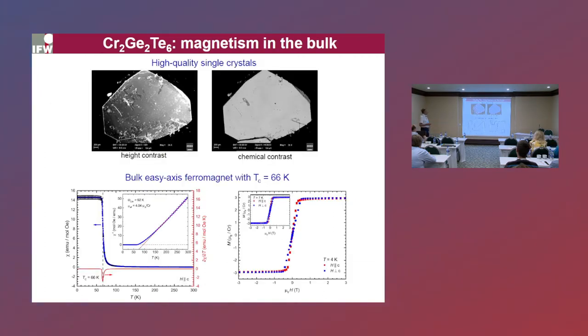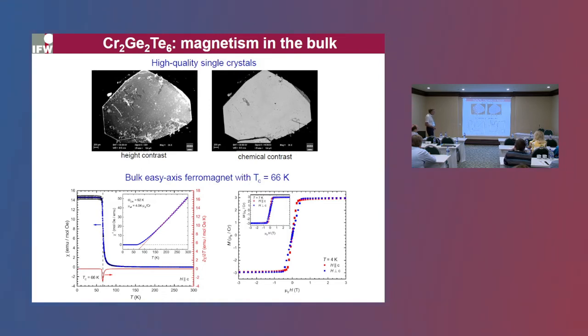Insights on magnetic anisotropy were required, and we attempted to obtain them in our measurements. We grew high-quality single crystals of this material — very flat and chemically homogeneous. We confirmed that in magnetization measurements there is a clear-cut transition to the ferromagnetic ordered state with a Curie temperature of 66 Kelvin. The magnetization curves are very similar for the in-plane and out-of-plane directions, suggesting it is a very soft ferromagnet.